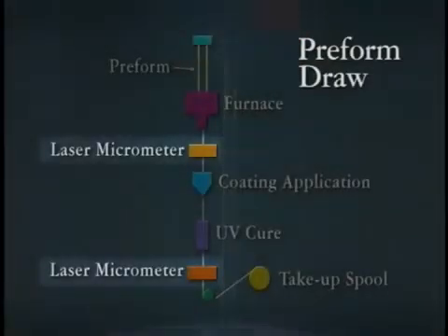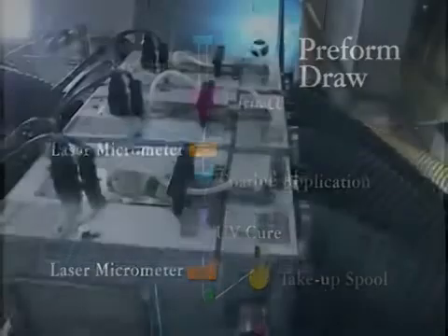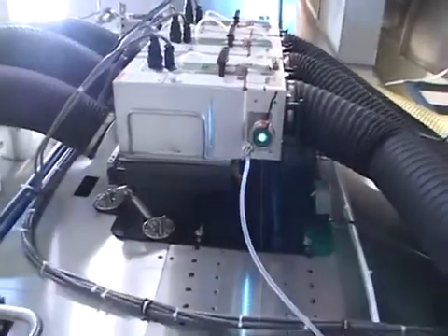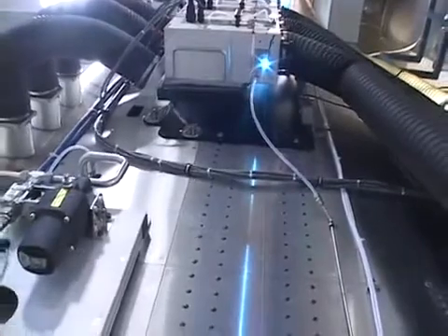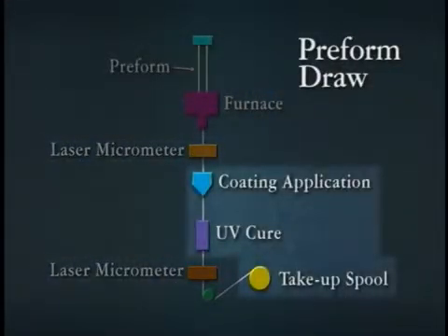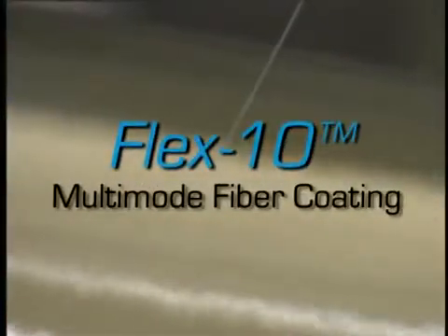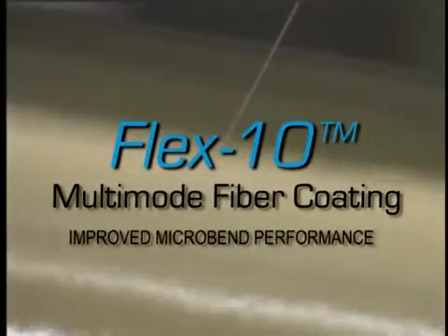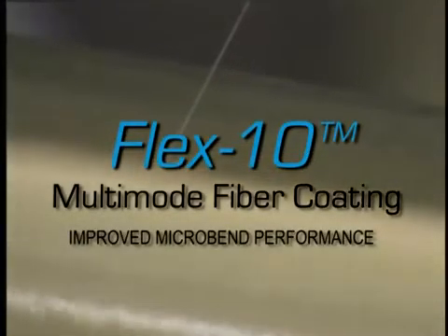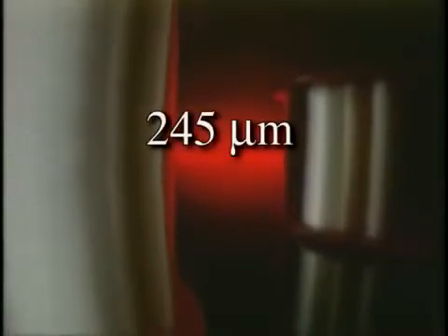Throughout the draw process, the fiber diameter is controlled to 125 microns within an extremely tight tolerance of a few tenths of a micron. A laser-based diameter gauge samples the fiber over 1,000 times a second, ensuring that precise dimensions are maintained. Before the fiber is put onto winding drums at the bottom of the draw tower, it's threaded through dies that apply a protective acrylate coating. Our Flex 10 coating protects the pristine surface of the fiber from the environment and makes the fiber easier to handle. Our fibers are available with 245 micron or 500 micron coating options.